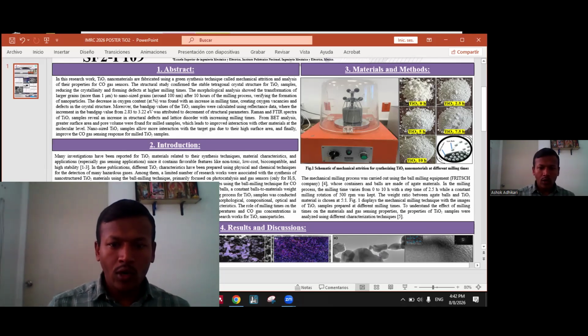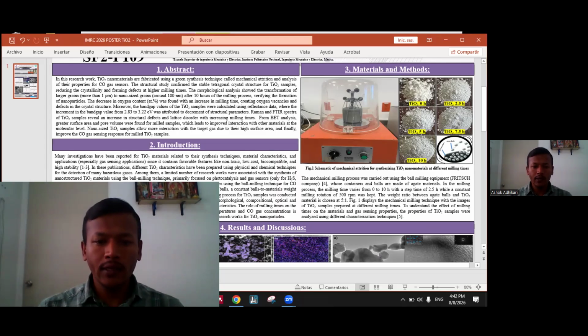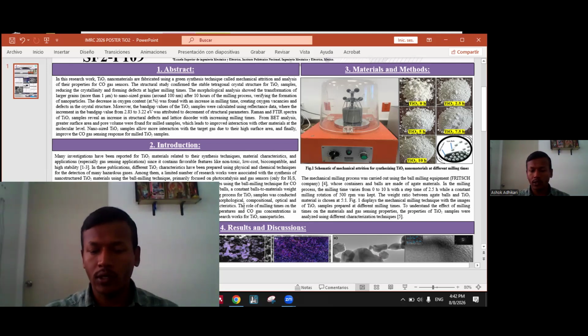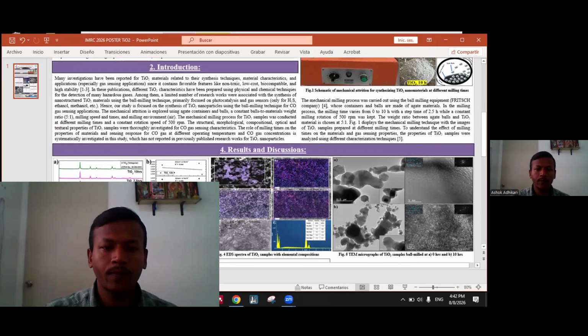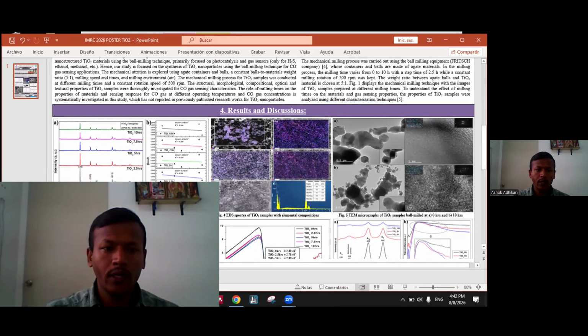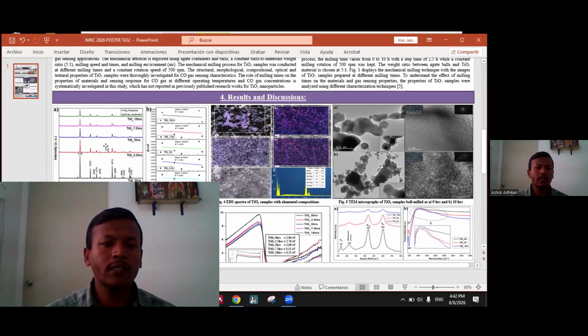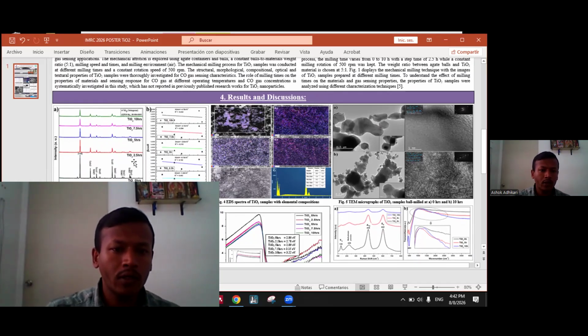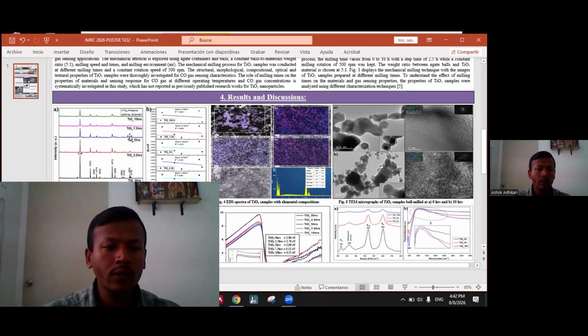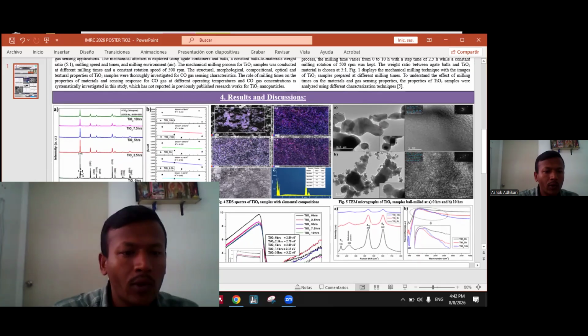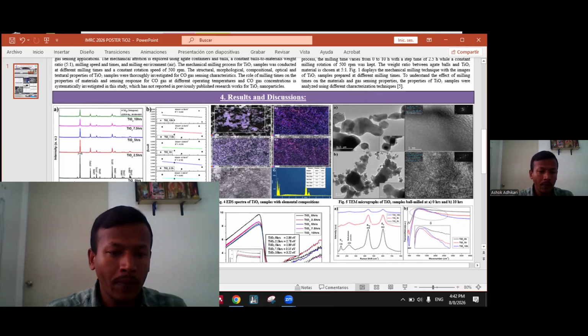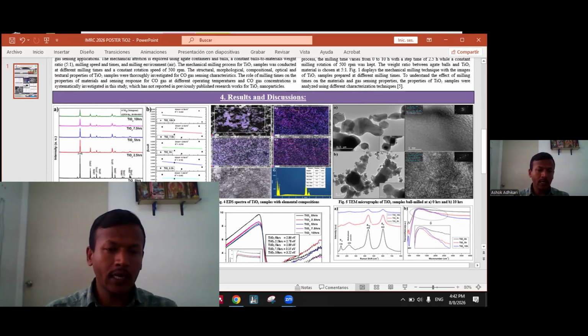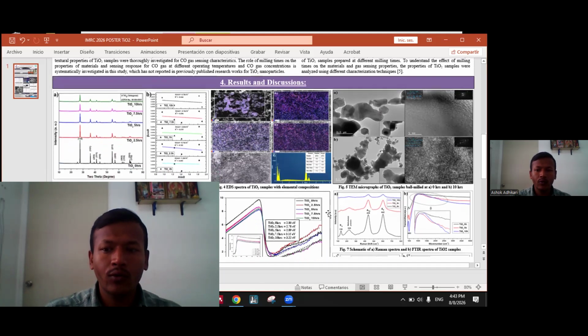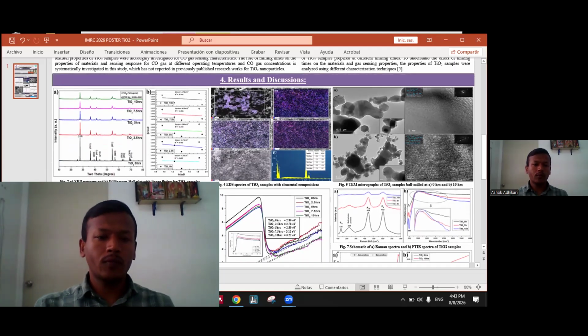So the role of milling times on the property of materials and sensing response for CO gas at different operating temperatures and CO gas concentrations is systematically investigated in this study, which has not been reported in previously published research work for titanium oxide materials. In the results and discussions section, initially we have presented the X-ray diffraction results, where we have the patterns from different samples from 0 to 10 hours. We have obtained various peaks, especially 110, 101, and 211, which are the main three peaks. All these peaks correspond to the tetragonal crystal of the TiO2. We have also calculated the interplanar distances, which are also compatible with the JCPDS number.